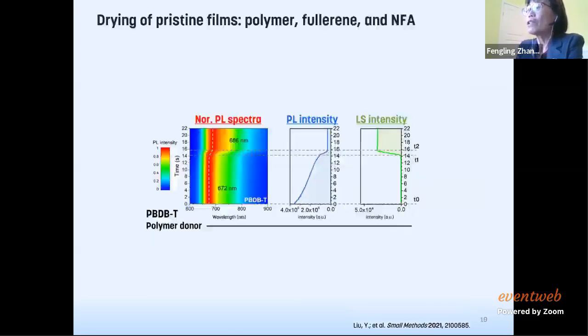So first, we try to image the pristine material drying process. So here is the image of the donor material drying. Then we can see the PL spectral shift with time, or we can say with the solvent evaporating, the PL red shifts. We also can see the PL intensity decrease with time, and the laser scattering increase with time. So you see the times correspond to each other very well.